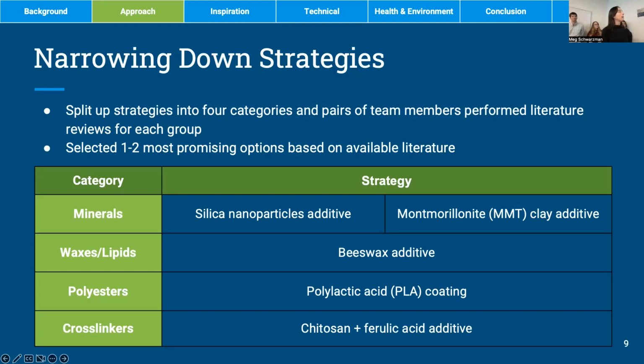What we ended up settling on were silica nanoparticles as an additive and montmorillonite clay as an additive under our minerals category. We chose a beeswax additive for our waxes and lipids category, polylactic acid coating for polyesters, and then a chitosan and ferulic acid combination additive for our crosslinkers category.